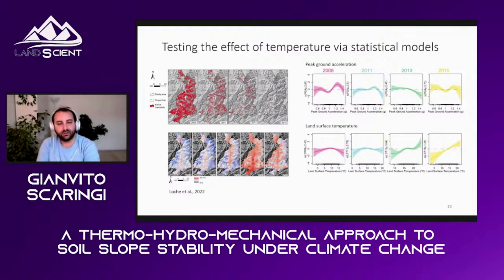What we found, quite interesting, was a good correlation between surface temperature and the abundance of landslides on certain slopes. It was found that for this material that is non-clay or non-active clay, so it's consistent with the laboratory analysis, warmer slopes meant more landslides, more remobilizations along those slopes. Quite interesting, but of course this is a statistical work, meaning that it can give insight, but correlation does not mean causation. So this requires an in-depth study.